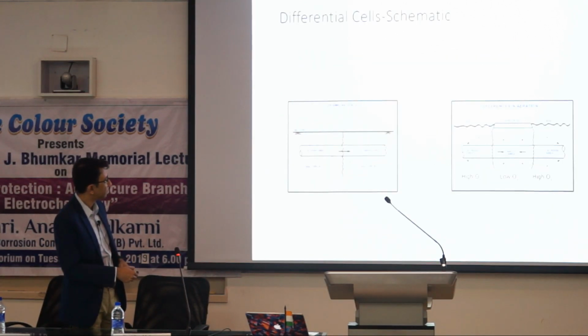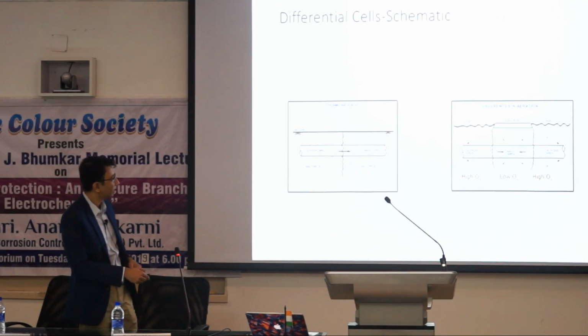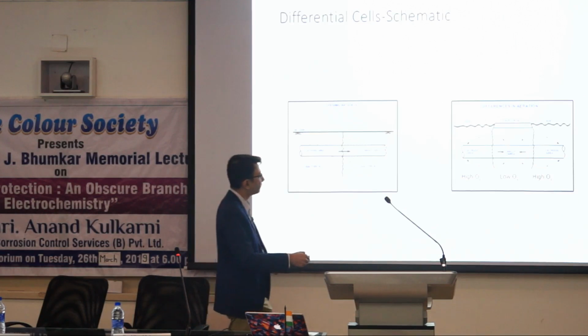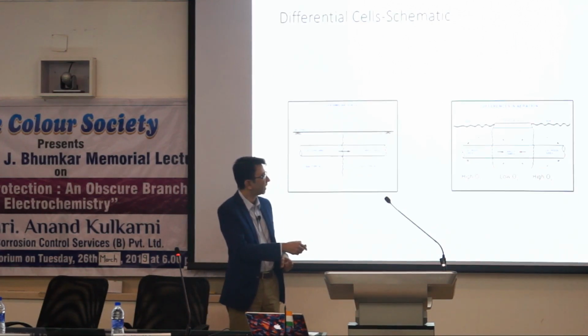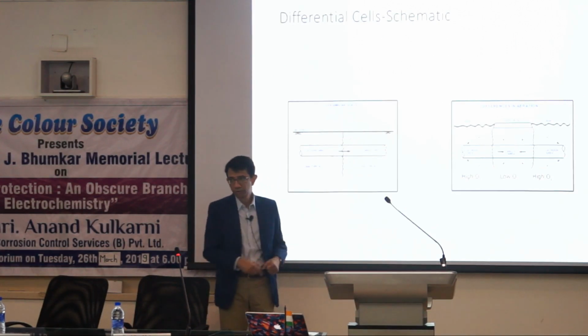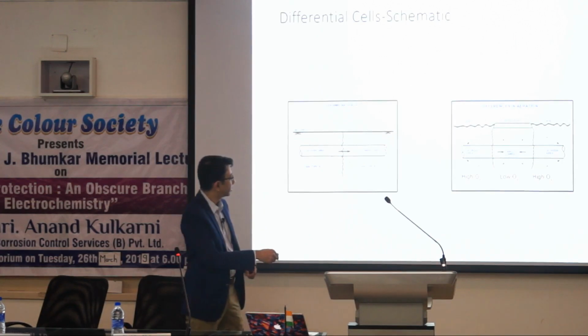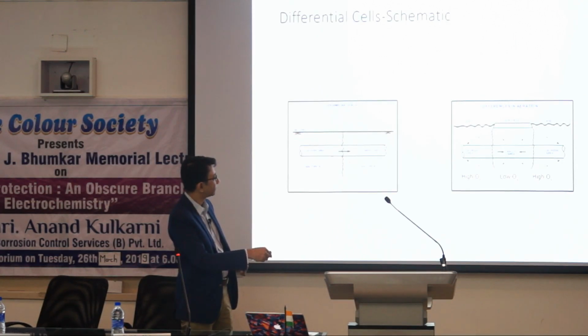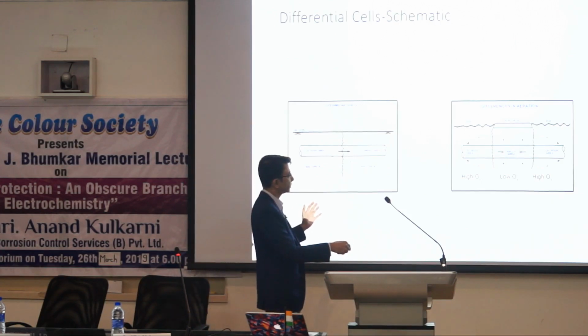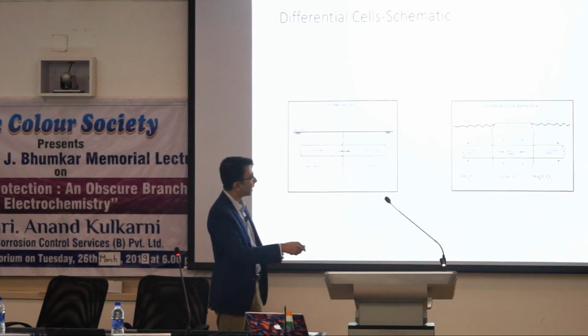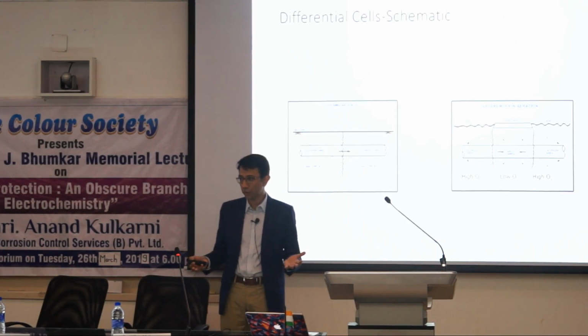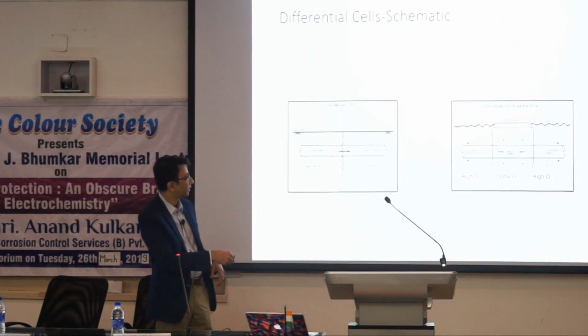Here is another example similar to the soil that we were talking about. You have a pipeline going under the road, and we find that under the road you have this area which is under the pavement, which is low in oxygen content. The section of the pipe on either side of the road is exposed to a perennial source of high oxygen because this is soil. So we find that if you have a situation such as this, the section of the pipe under the paved road is going to become anodic compared to the other two areas,